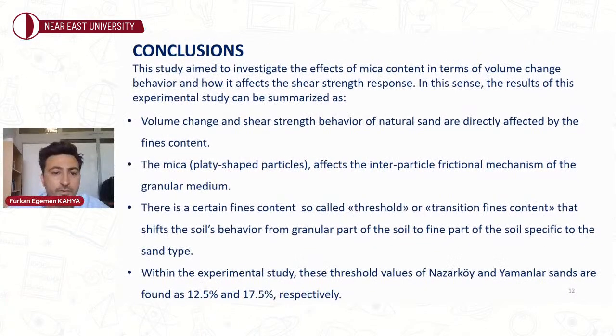This study aimed to investigate the effects of mica content in terms of volume change behavior and how it affects the shear strength response. In this sense, the results of this experimental study can be summarized as follows: volume change and shear strength behavior of natural sand are directly affected by fines content. The mica affects the interparticle frictional mechanism of the granular medium. There is a certain fines content, the so-called threshold or transition fine content, that shifts the soil's behavior from the granular part of the soil to the fine part of the soil, specific to the sand type.